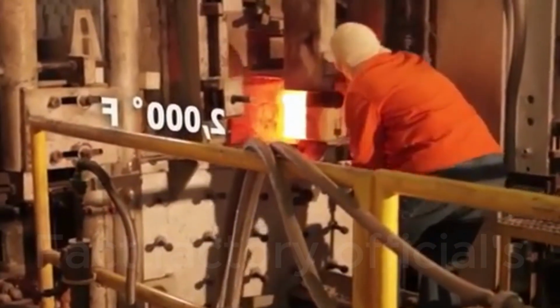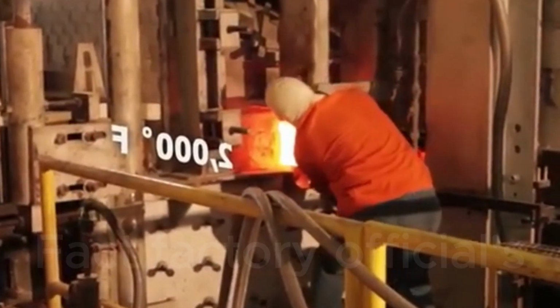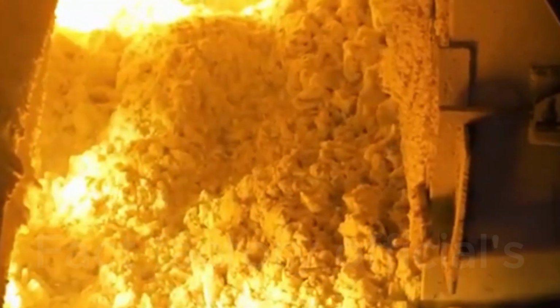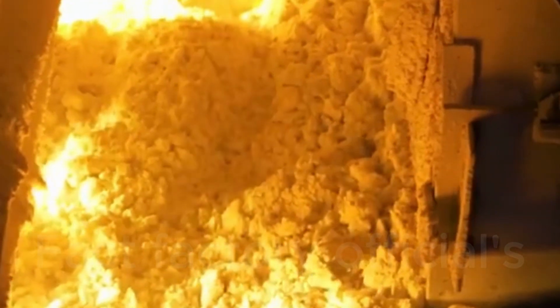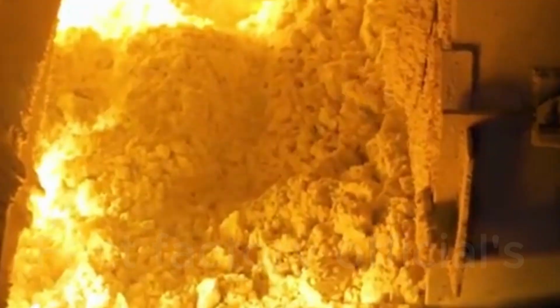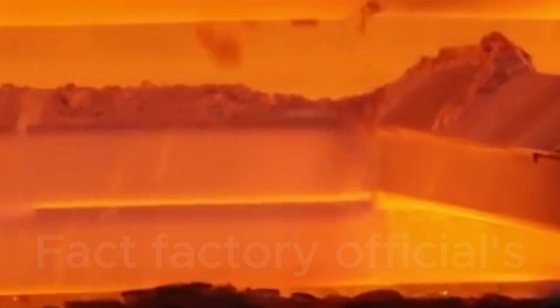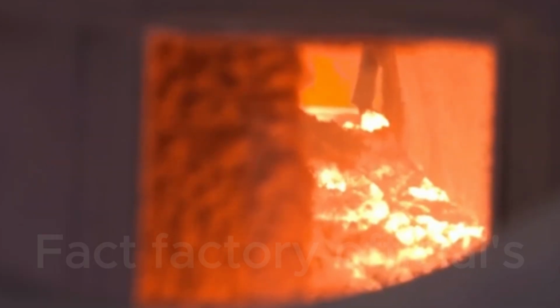Once the molds are finalized, they are installed into the double-blow production line, one of the most widely used methods for shaping hollow glass items, like soft drink bottles, food jars, or pharmaceutical containers. The process begins by releasing drops of molten glass, known as gobs, into the preliminary mold. These gobs are cut from a continuous stream of liquid glass, reaching temperatures up to 1,100 degrees Celsius and possessing the ideal viscosity for smooth shaping without excessive deformation.